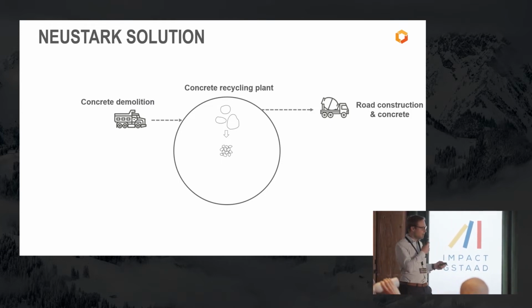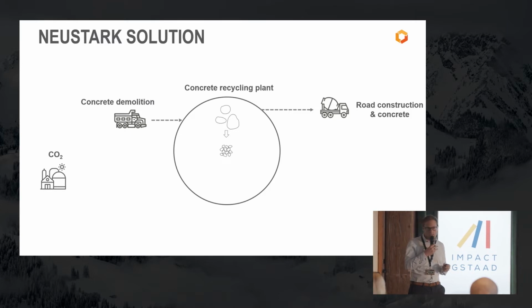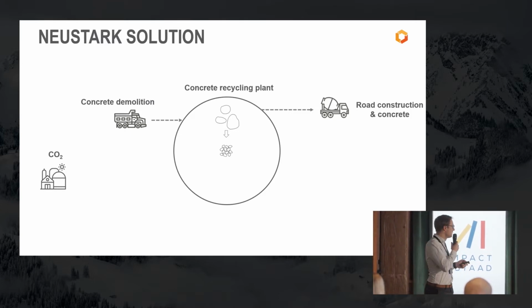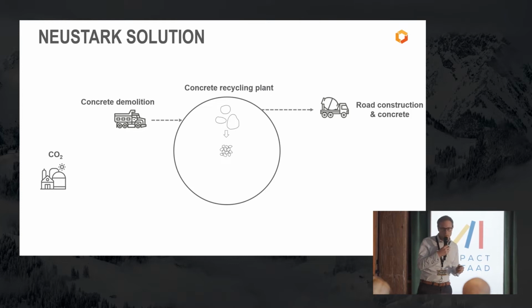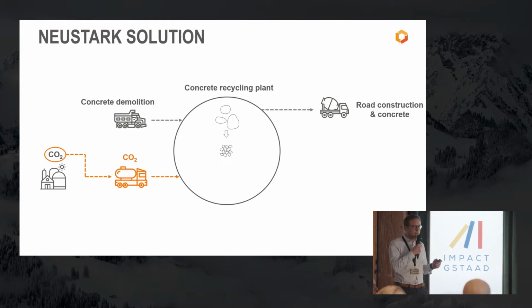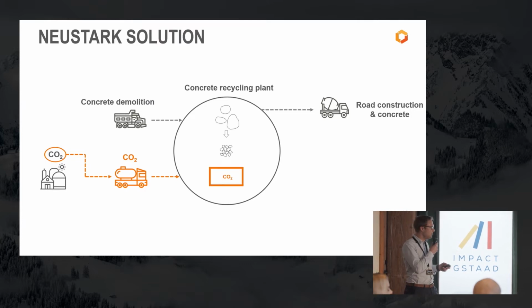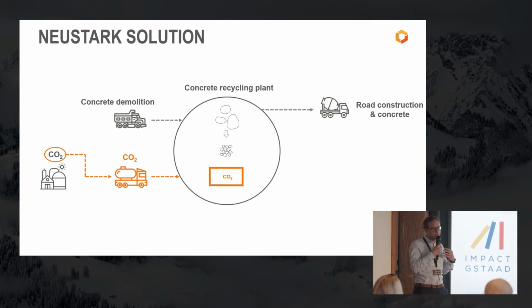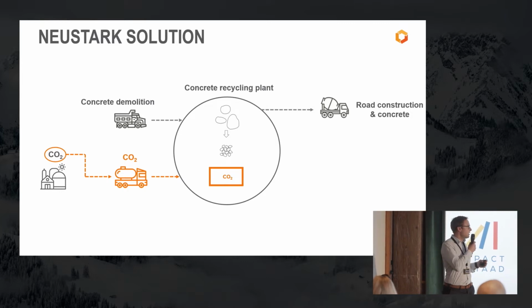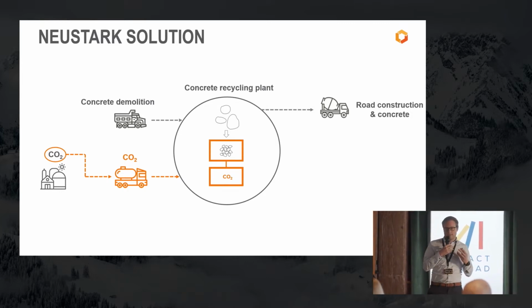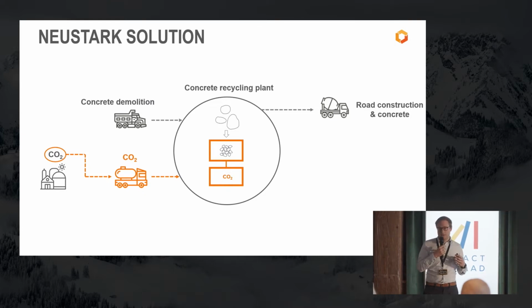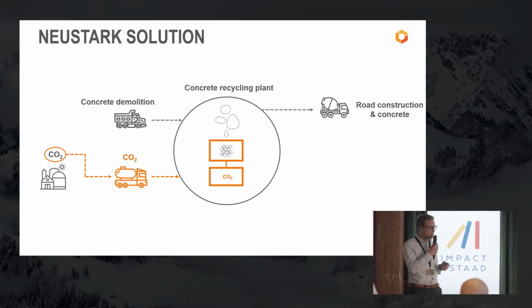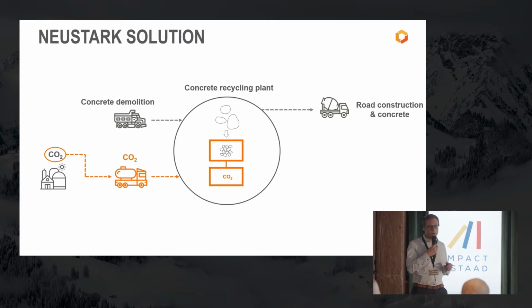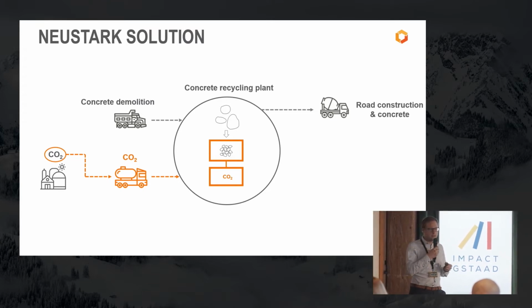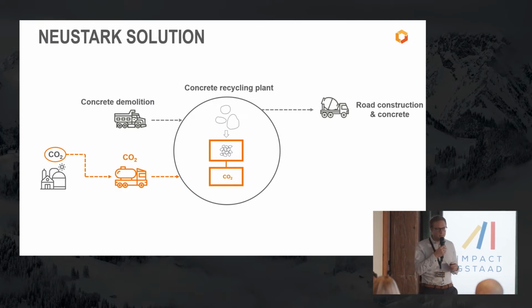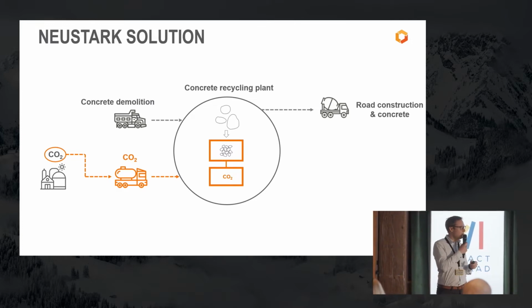And what we do at Neustark is that we have already today biogenic CO2 sources, for instance biogas plants. They upgrade biogas and produce a pure CO2 stream. We capture the CO2, liquefy it, transport it to the concrete recycler, and afterwards we install our mineral carbonation technology on site, where we basically treat the concrete aggregate with CO2. The CO2 undergoes a chemical transformation to solid calcium carbonate in the concrete aggregate. And this way the CO2 is permanently stored, and afterwards this material can be reused as before for road construction and concrete.